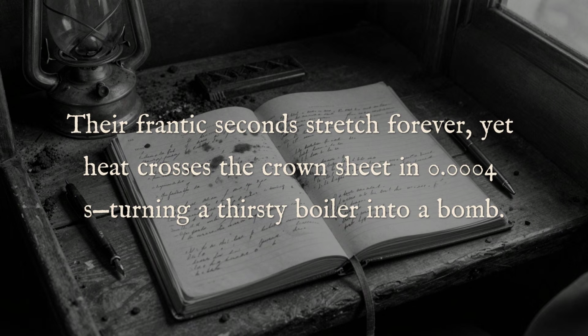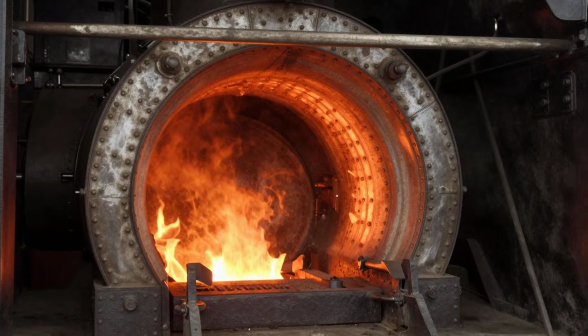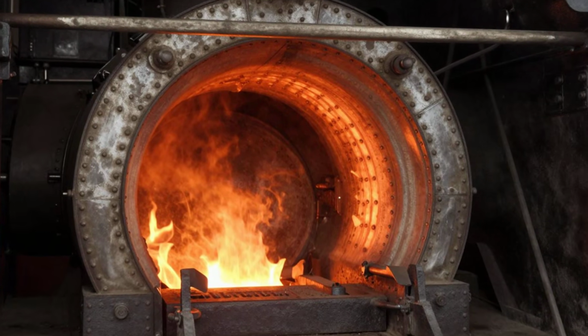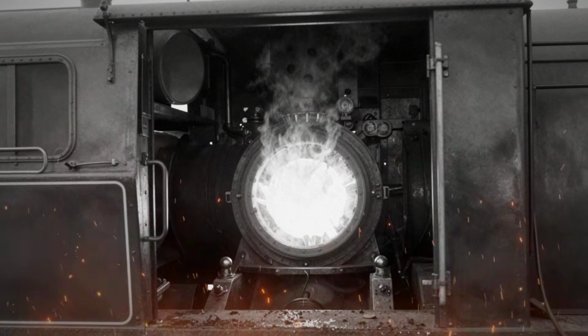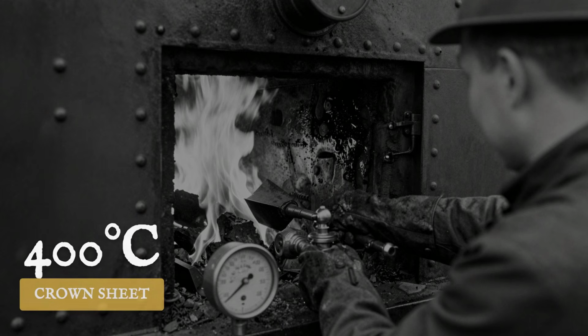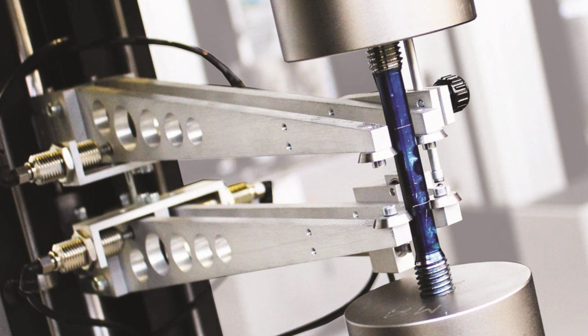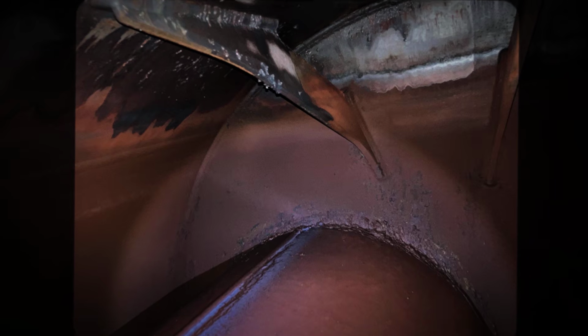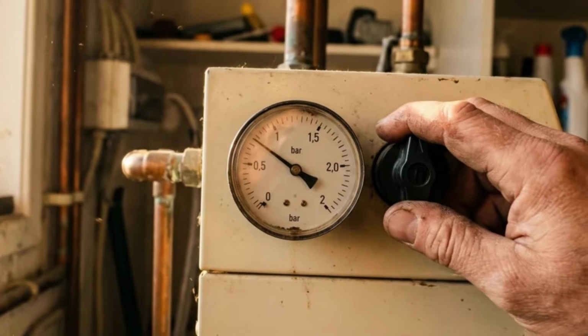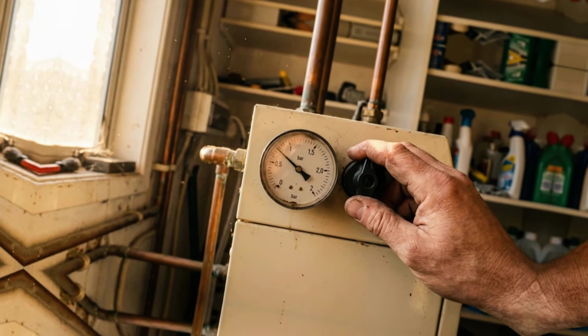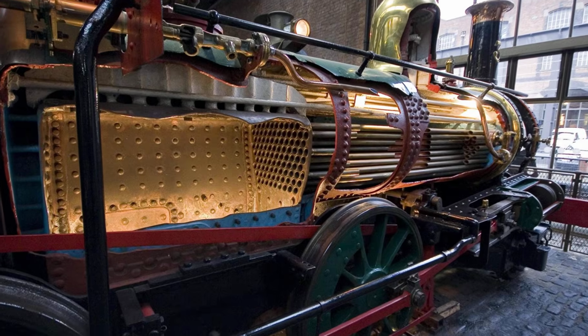Crew log. Injector failed. Water not rising. Attempted restart. No effect. Crown hot. Seconds drag. The firebox glows white. The crown sheet, now exposed, spikes past 400 degrees Celsius. Tensile yield limit falls off a cliff. The steel is no longer a barrier. It is a fuse. The engineer grabs the blowdown valve. Too late. The water film is gone.